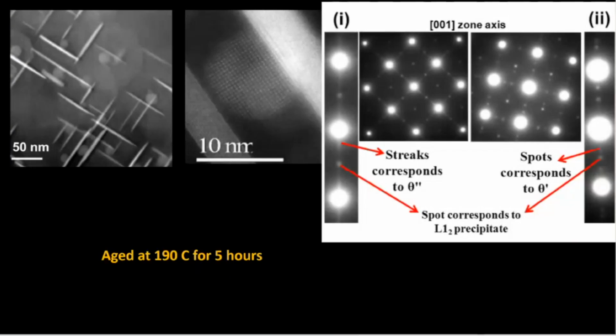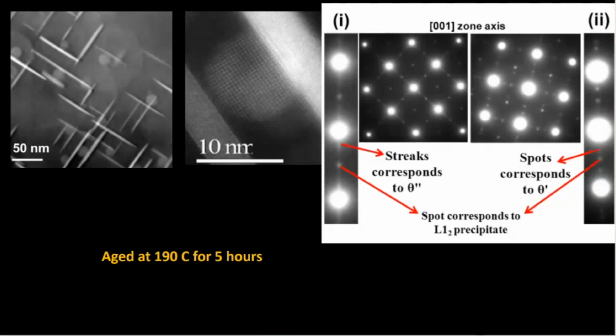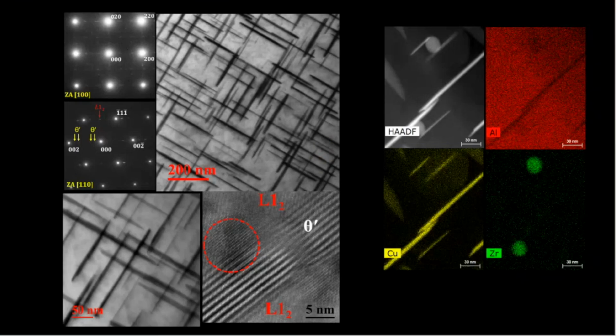At 190 degrees centigrade, at lower temperature, we give an aging treatment. Pre-existing L12 precipitates act as heterogeneous precipitation sites, and that nucleates both theta prime and theta double prime precipitates. On the right-hand side, diffraction evidence of these two precipitates is shown. This is what you see in the microstructures, that all these plate-like precipitates are nucleated on L12 precipitates, and they are basically the aluminum copper precipitate. You only see the theta prime, which consists of aluminum and copper, and the matrix only contains L12 precipitate.